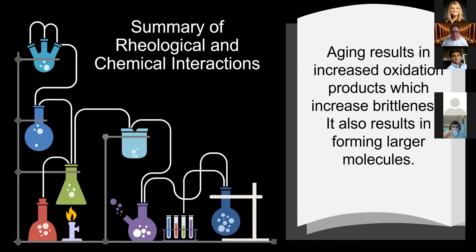So a general summary, an oversimplification probably, of the rheological and chemical interactions is that aging results in increased oxidation products, which increases brittleness. It also results in forming larger molecules. Those two major pieces can be seen in all of that rheological work and chemical work. And we feel that we can use those parameters to quantify the performance and effect of modifiers as they age.